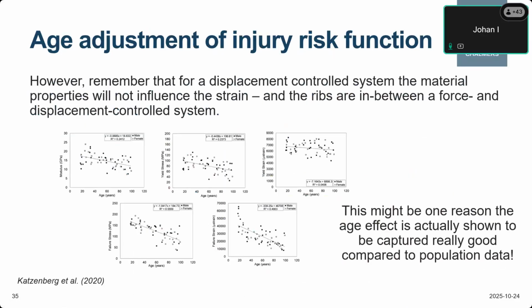So if we now remember that for a displacement controlled system, the material properties will not influence the strain. And we also remember the ribs are somewhere in between a force and a displacement control system. If the material properties don't decide how much strain we get, then the modulus, the yield stress, the yield strain, and the failure stress are not really important. So speculating, this might be one of the reasons the age effect is actually shown to be captured really well compared to population data.